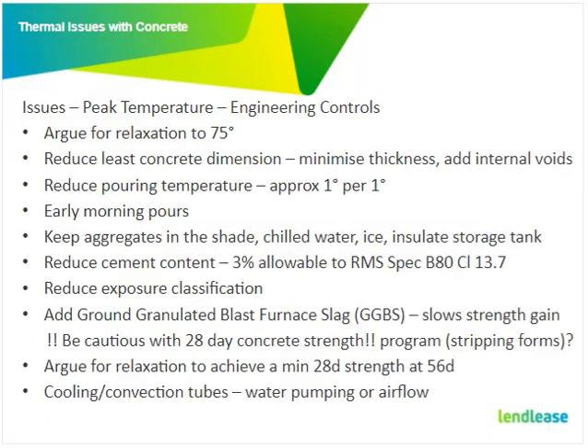What are some of the engineering controls that you can deal with for peak temperature? Get a relaxation to 75 degrees. Reducing your least concrete dimension is another one of those things that has a direct impact on peak temperature. You could add internal voids. As I explained before, reduce the pouring temperature. So if you can get that right down, that's a good thing.